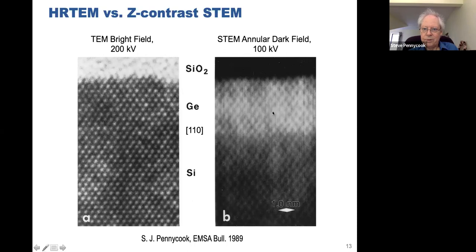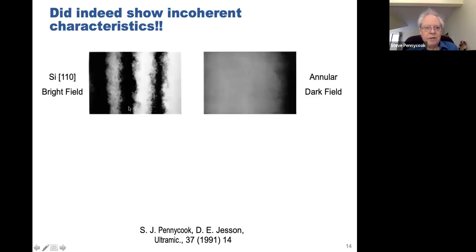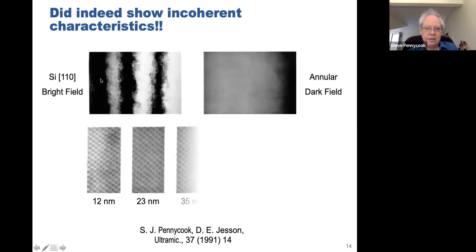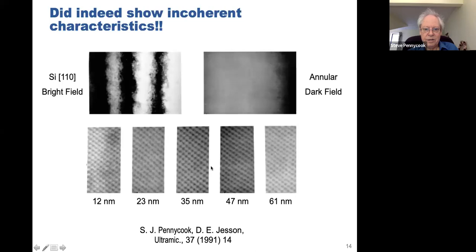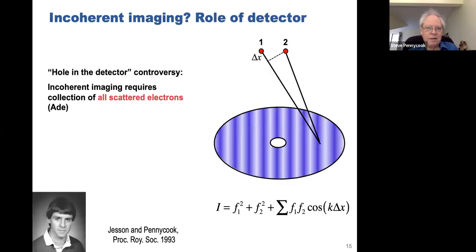And actually, if you look really closely, although this is poor resolution by today's standards, put the structure on there, you can see these features are not circles. You can actually interpret the elongation to indicate there must be at least two columns of atoms spaced below the resolution limit. So this is a characteristic of incoherent imaging. It maintains interpretability even beyond the resolution limit. Here you have thickness fringes in silicon 110, interference image in bright field, and in dark field here, practically no sign of the interference at all. And this is convenient. You can look at the image at all of these different thicknesses, and basically it doesn't change in form. So that was the birth of incoherent imaging.